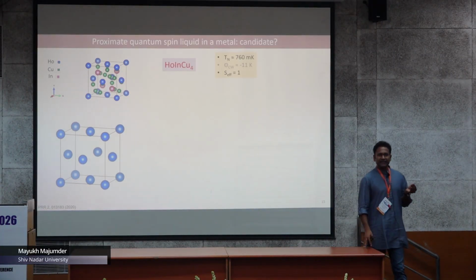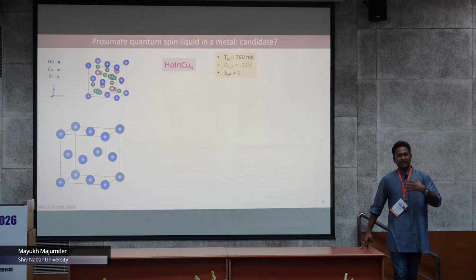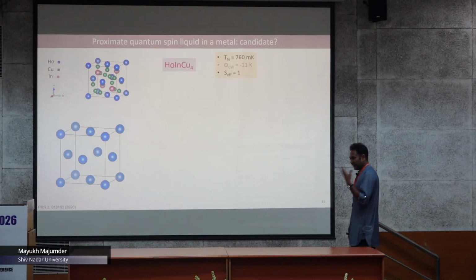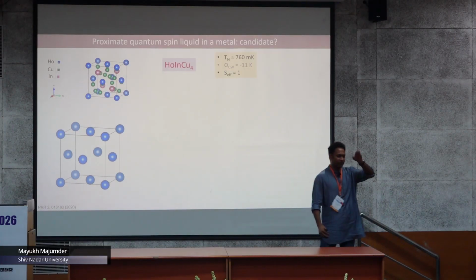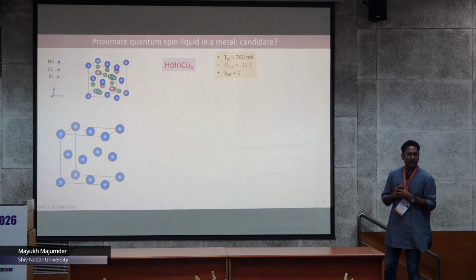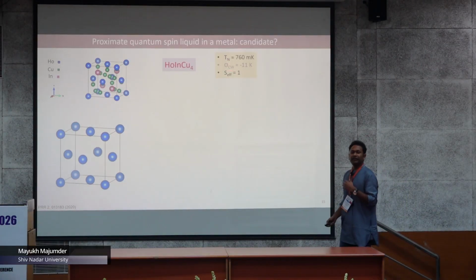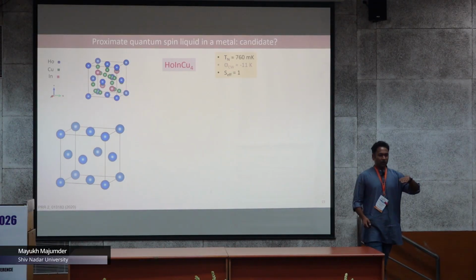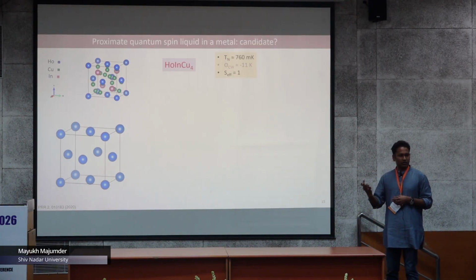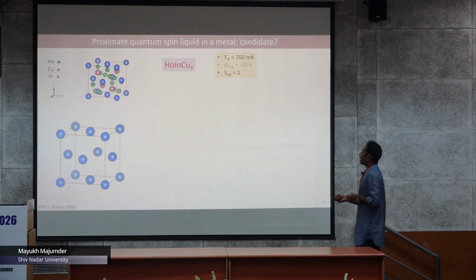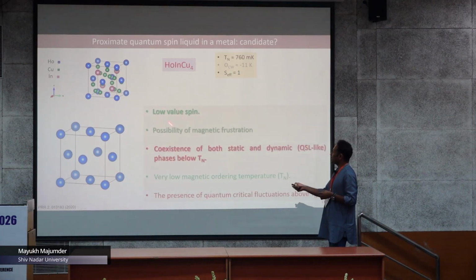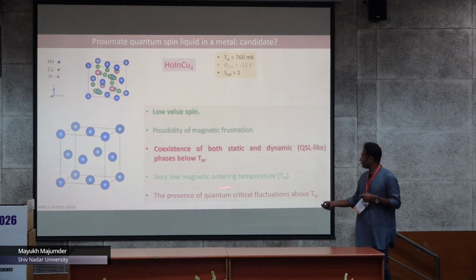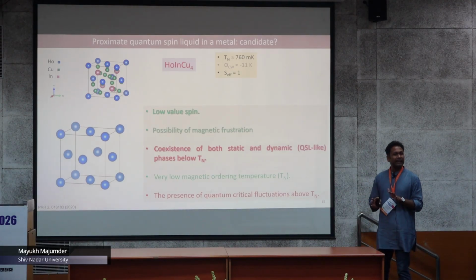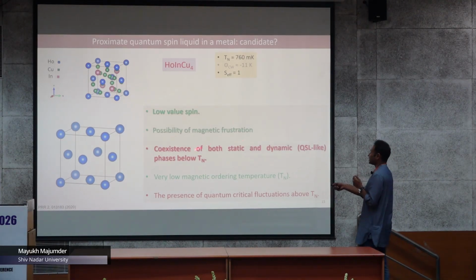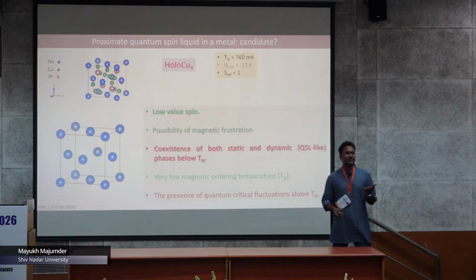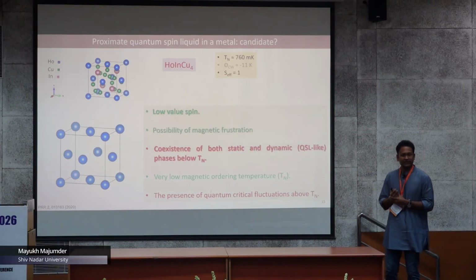However, the Curie-Weiss theta in the case of a metal does not really give you the strength of the frustration, because at higher temperature you have Kondo and other stuff going on. Okay, but the point is that the ground state is sort of an S equal to 1 ground state because of the crystal electric field. Okay, so now you can see that for this particular compound, out of these 5, 3 conditions are getting satisfied. Yet to be explored is whether there is indeed a coexistence of static and dynamic correlations or not.